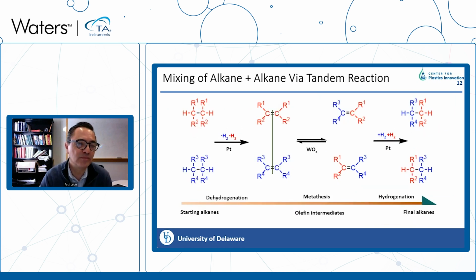And so when we're trying to mix alkanes, or two different alkanes, we need to use a tandem reaction or a bifunctional catalyst. And so we are going to have two components, one which is based on platinum, and the role of the platinum is to remove a small amount of hydrogen from these alkane chains to produce a small amount of olefins as indicated here. Then these olefins are going to go to a second catalytic material. In this case, we're going to use a catalyst based on tungsten oxide that will do the metathesis chemistry.